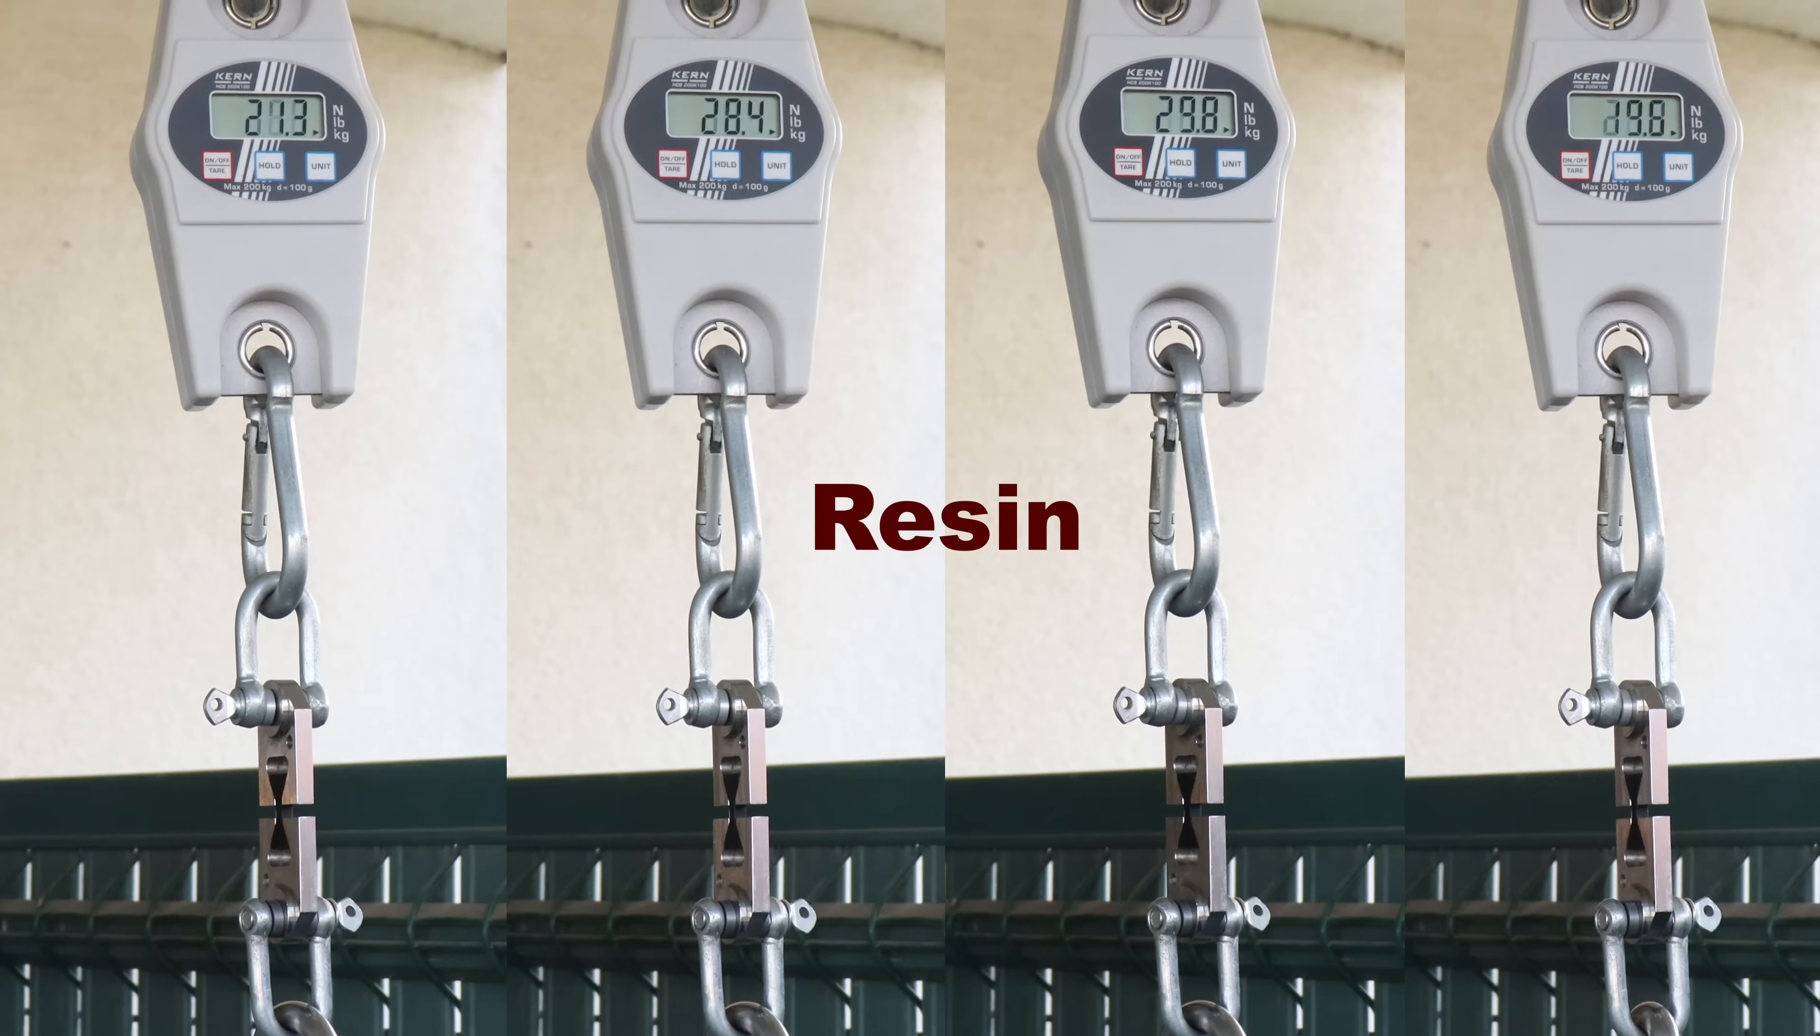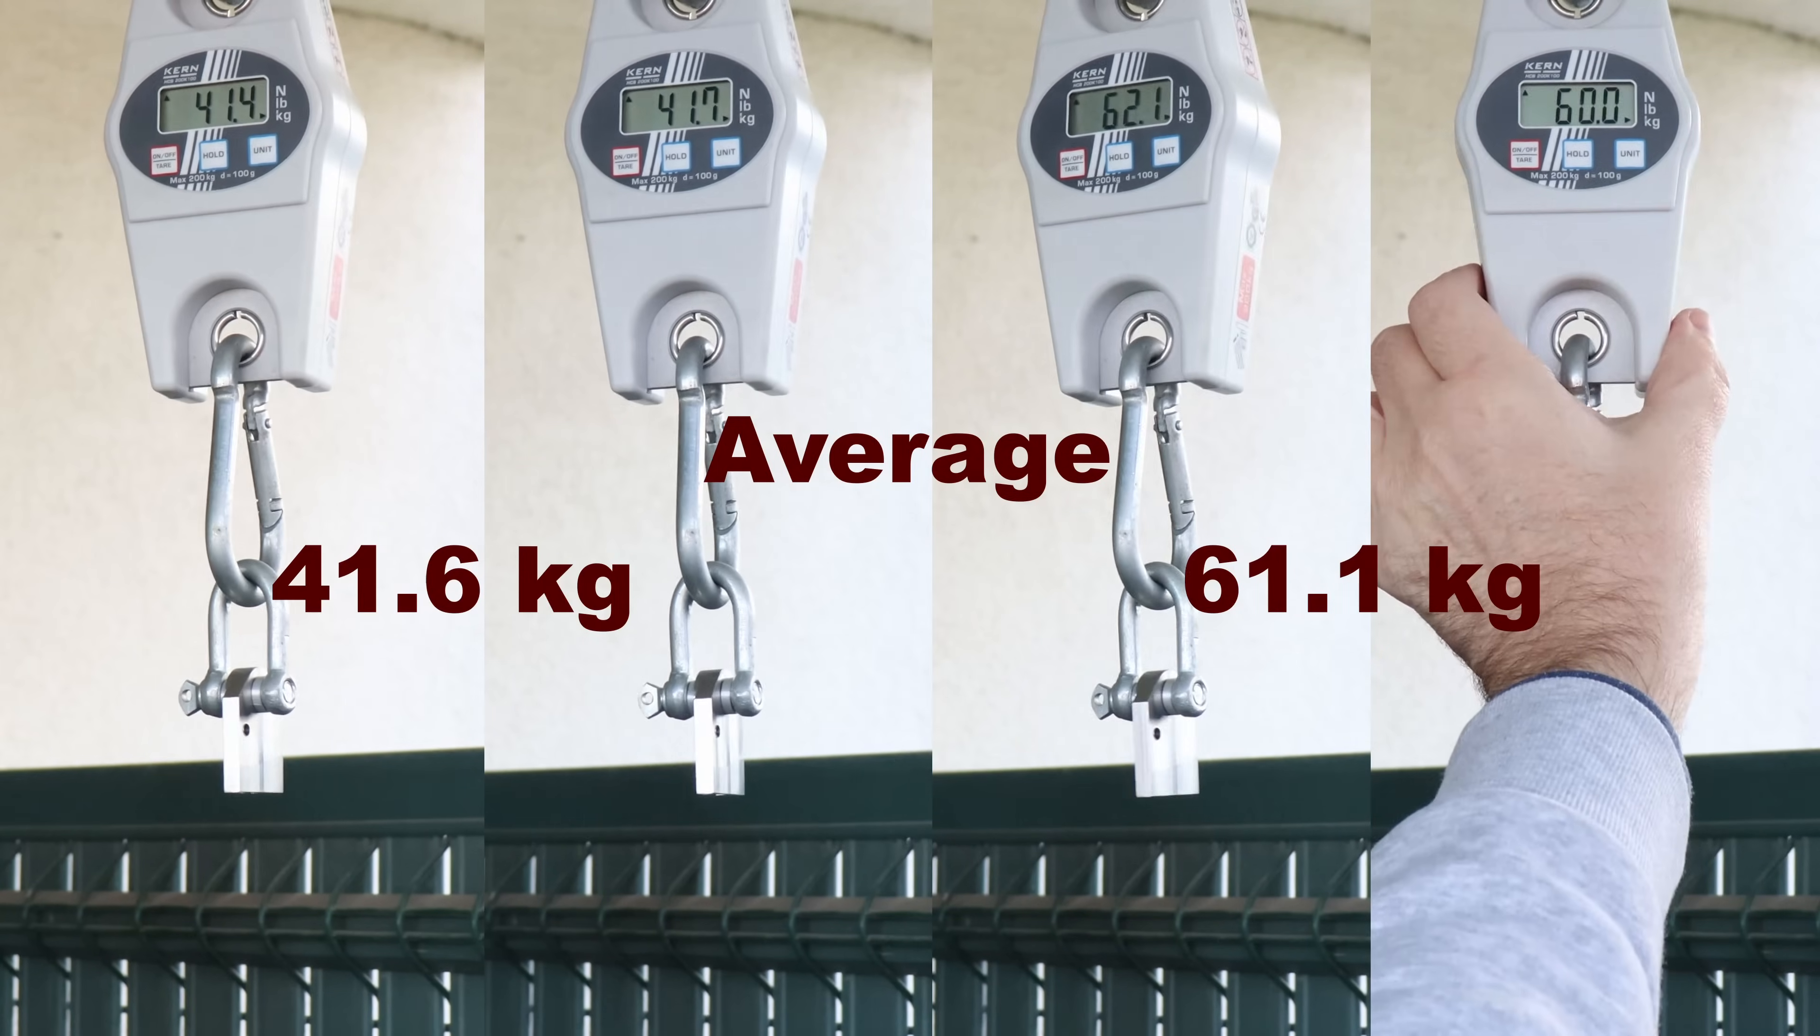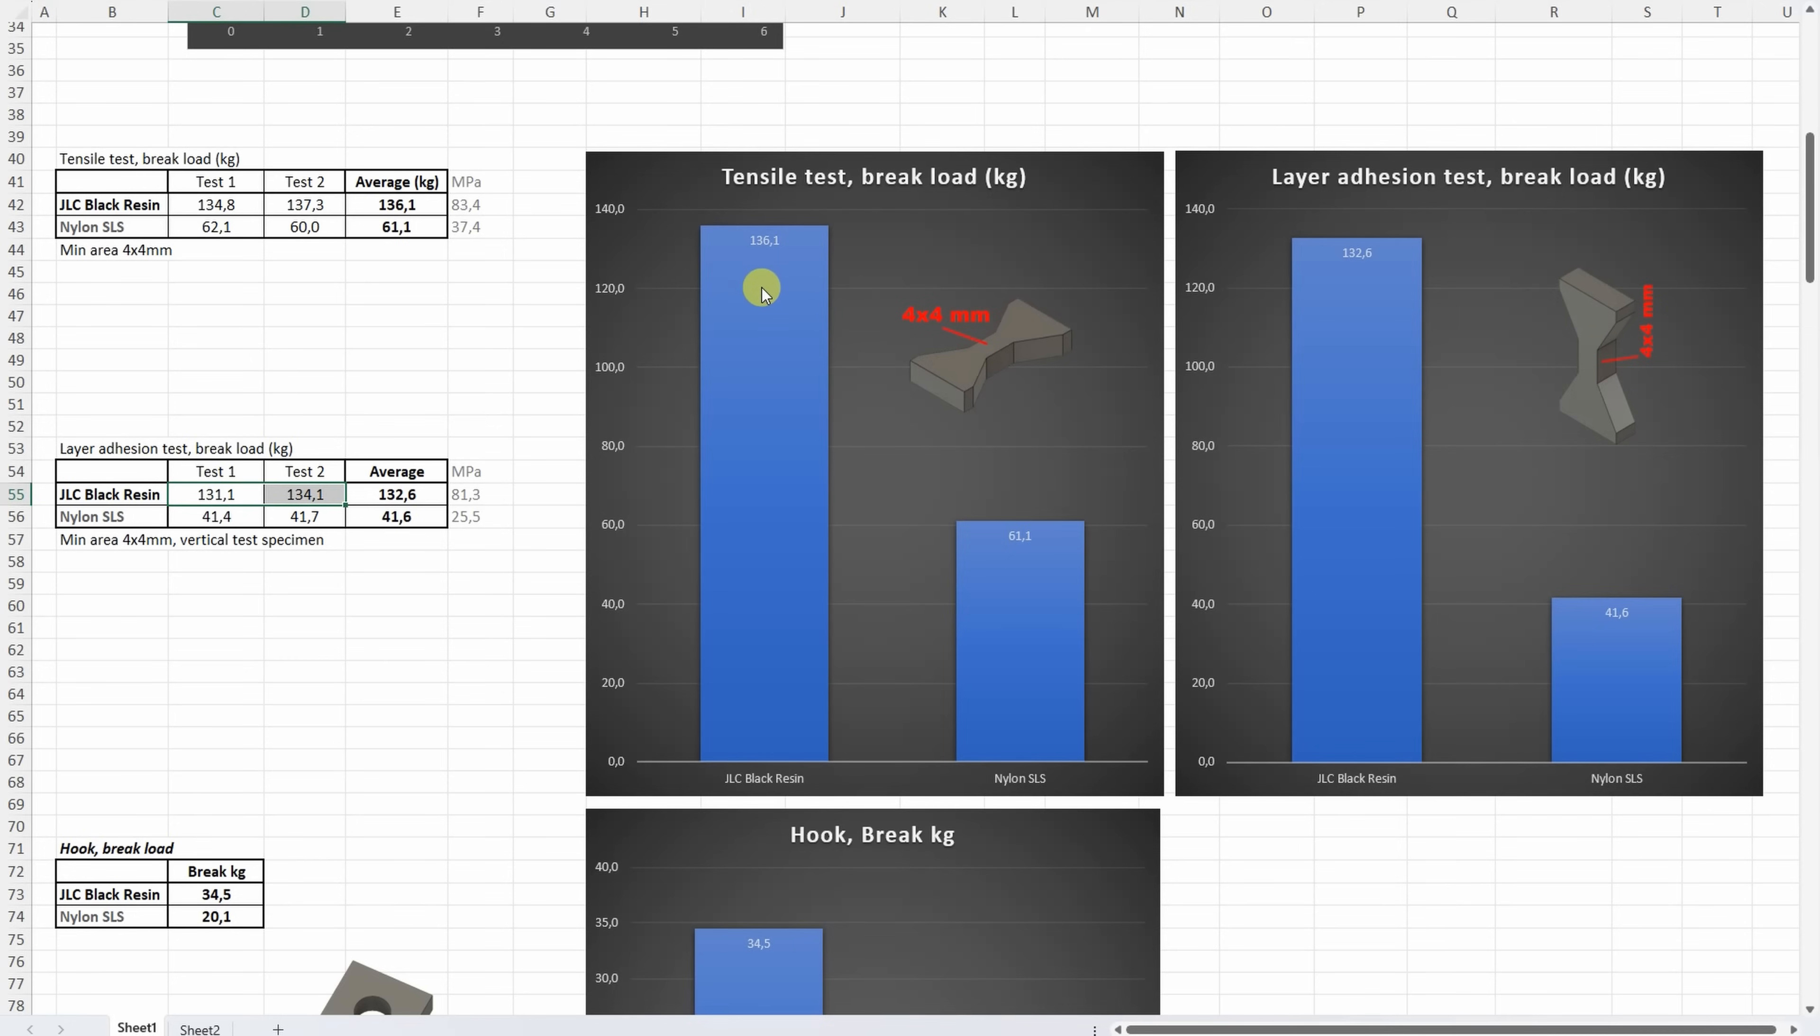This is a tensile test and I'm starting with the resin. Very similar numbers in all four cases. And this is the nylon and here you can see some differences depending on the orientation of the printing and I really like this break surface when it is not along the one layer. I got a request to analyze the data immediately after the testing so let's try that version. On the tensile test we can see that with the resin printing, SLA printing, there is no big difference if printed in horizontal or vertical position and this means that with this JLC black resin we don't have that weakness along the z-axis. Until with the nylon we can clearly see that approximately 50% stronger is the version which is printed horizontally.